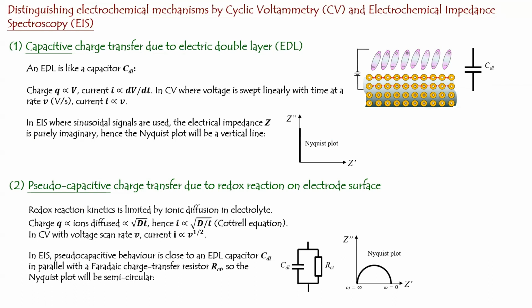Okay, if you have the EDL mechanism, going back to that cartoon, in terms of electric circuit, this is like a capacitor. So if you do potential switching across the capacitor, you would know that the capacitance in terms of the impedance plot is purely imaginary, meaning that the current will have a 90 degrees phase difference with respect to the driving voltage. Okay, so if you see a vertical line in the Nyquist plot, you can infer that the mechanism is EDL.